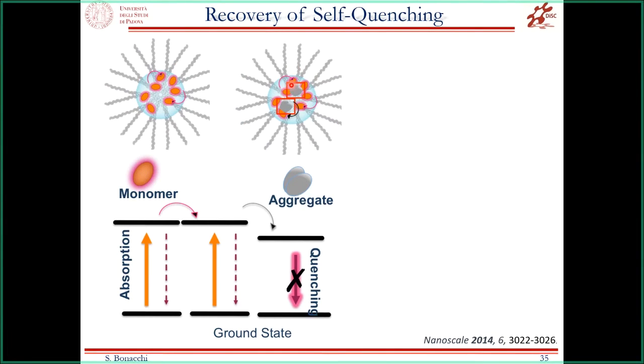But as soon as we start to increase the loading, there is an aggregation effect among rhodamines inside the silica core, and this aggregation is well known to be characterized by a lower excited state that acts as a trap of the emission. This determines the decrease of the fluorescence as soon as we increase the loading of rhodamine. And so we thought about a strategy to recover this quenching effect, to actually increase the brightness of this system.